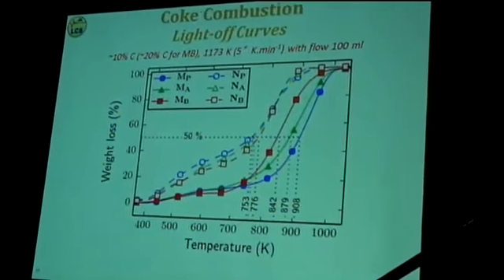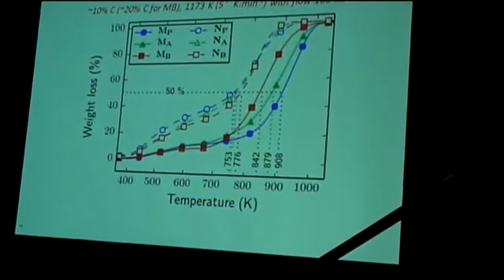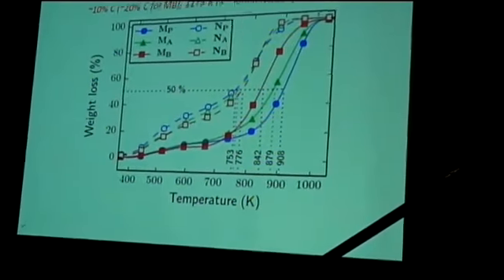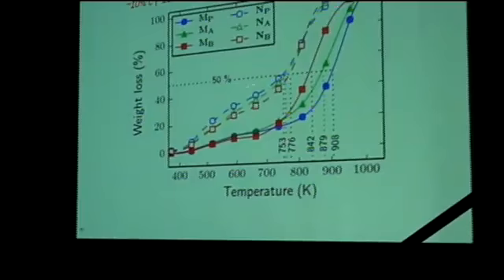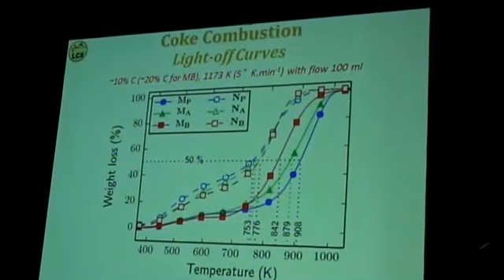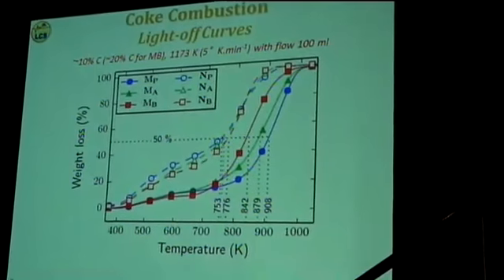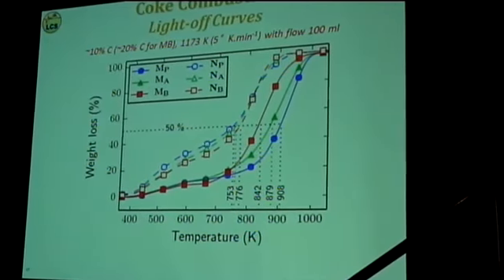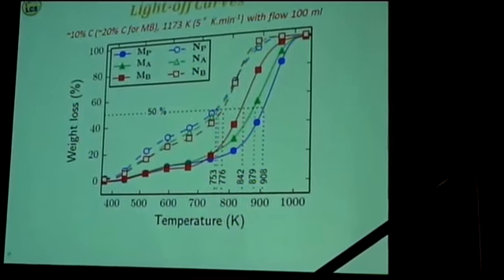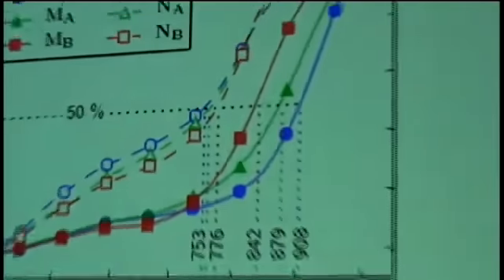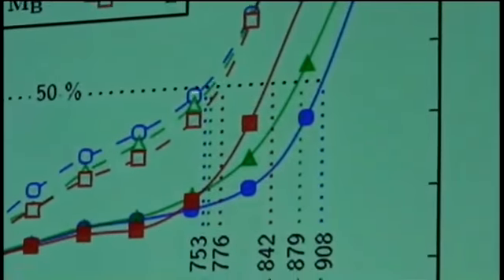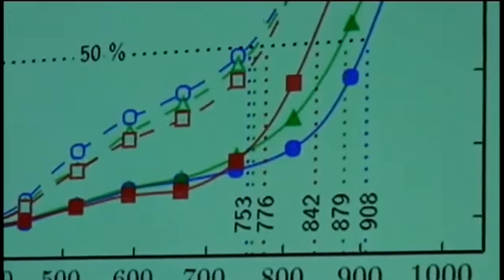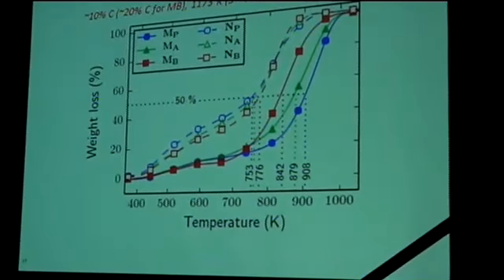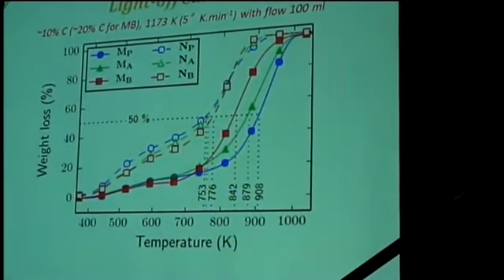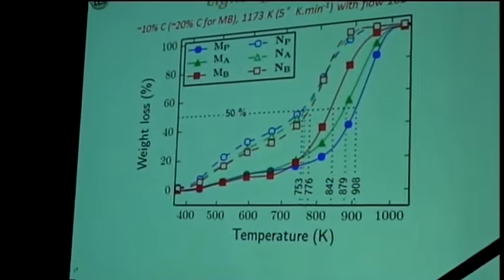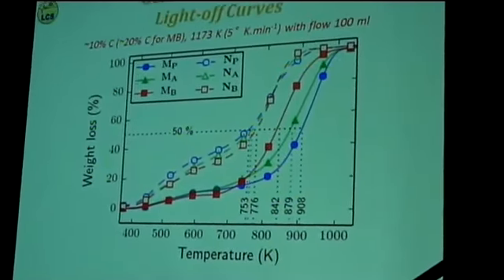Again, here we see two different families of material. We see the nano-sized crystals, in blue the parent and then the post-treatment of the parent, but you see there is not a big difference. There is a big difference between the nano-sized crystals and the micron-sized crystals. In order to remove about 50% of the coke, there is about a 150 degree K difference. So it's a very significant difference. Again, it means that it's much easier to decoke these nano-sized crystals than the hierarchical materials.